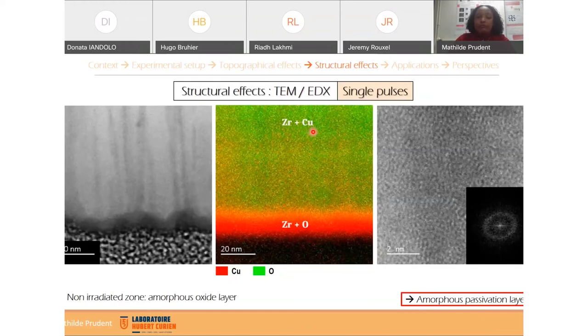But here we have some amorphous layer. It seems to be an amorphous passivation layer containing a lot of zirconium and oxygen. In the EDX mapping, we just represent here the copper in red and also the oxygen in green because it's much more visible, and the zirconium is approximately homogeneously distributed in all of the zones.